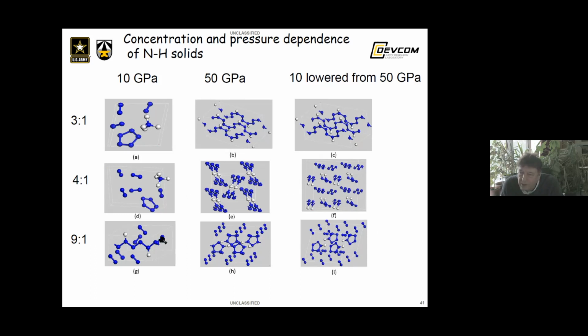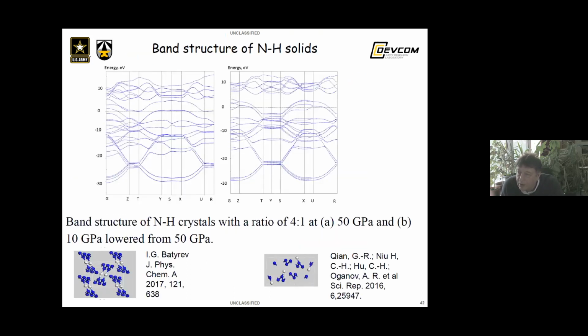Most of the structures are insulators, and only these two structures are metallic. So these are results of calculation of band structure of these two metallic structures using hybrid functional. And this is a structure at 50 GPa. From our perspective, it's nice to have a system with a high energy density and high burning power. So this is again the structure predicted, and it's kind of similar to the structure predicted by Artem Oganov's group, but it is more symmetric and has a lower enthalpy.